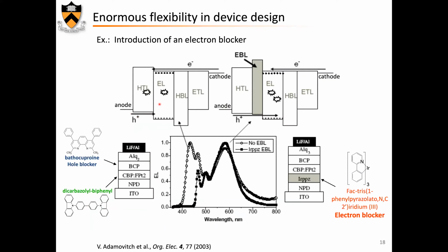What you want is a recombination of electrons and holes in this electroluminescent layer. So electrons come in and holes come in, and yes, you do have some recombination here, but you also have recombination in this layer because there's really no good barrier for electrons here. An electron penetrates this HTL, this layer, and that leads to an undesired double emission peak. You do not want this peak. You want really only this one, which comes from this electroluminescent layer.